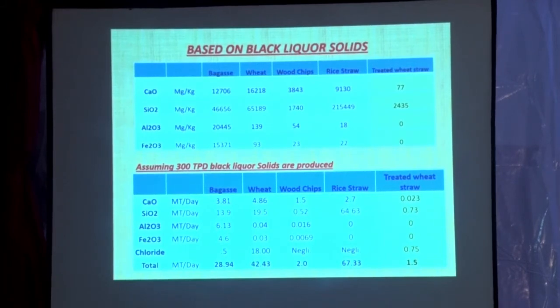If you remove or reduce this dead load, the solid generation will reduce to 1.1 ton per ton of pulp. Means there is a leeway to increase the pulp production also. And this dead load, 50 ton dead load, doesn't have any contribution in steam generation or green liquor generation. These are just dead load. If you remove the dead load, GCV of the wheat straw liquor itself will increase to 3,200 kilocalorie per kg, which means it is better than wood liquor. See the data. This is the treated raw material interpretation.